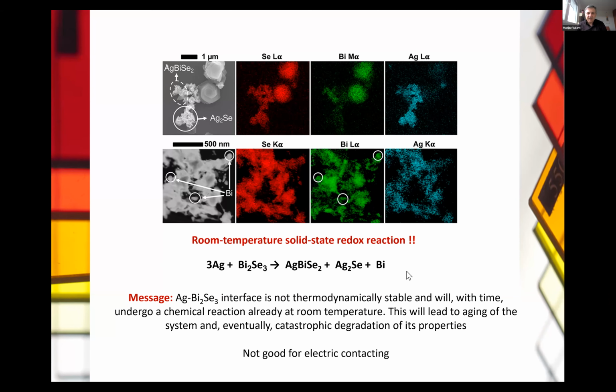redox reaction that occurs when we deposit silver on top of bismuth selenide. In this case, we get two selenides, ternary and binary selenide, in addition to metallic bismuth. Certainly, silver is not good as an electric contact for a topological insulator, because it will degrade with time and we will lose it. So let's go on then.